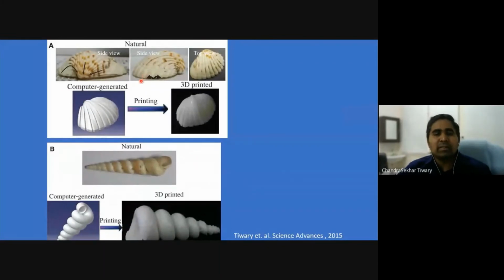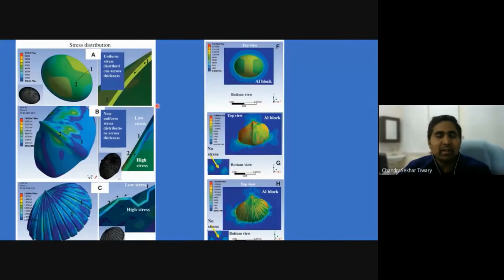And what we started understanding, the first work we did in 2014-15, where we took the sea shell structure, made the AutoCAD design of it by measurement, and finally we built the 3D printer and printed it. We took two of the models and did that. And then in collaboration with Mahapatra in aerospace, we did the FEM analysis, where we try to understand the role of individual complexity. For example, if I take the same sea shell structure with a spherical shape, what happens if you deform it?